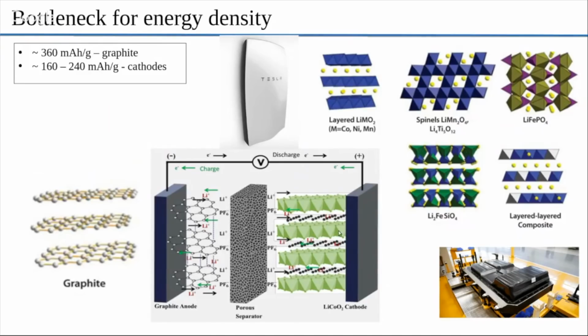So all of that we are talking about on this side, and this side is the bottleneck. This side is the problem. The positive electrode, the cathode, is the problem. They have lower energy density than graphite, between 160 and 240, 230 on the higher end. As they say, the strength of a chain is in its weakest link. So the energy density of a cell is dictated by the energy density of the cathode, the positive electrode. Graphite is able to store much more lithium, but the cathode is unable to hold that much lithium. So unless we increase the energy density of cathodes, we may not be able to push beyond.